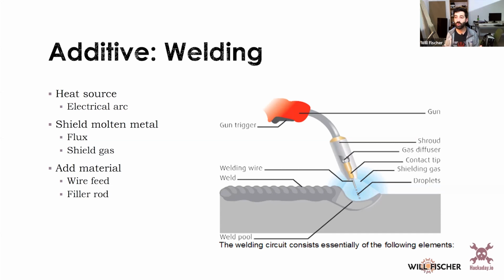And so I have two ways to do that. Either I can use flux, which is a material that floats to the surface of the weld pool, hardens, and then keeps the oxygen away from the weld while it's cooling. Or the much preferable way to do it is with shield gas. Shield gas displaces the oxygen around the weld and fills it in, typically with argon or CO2, or a blend of argon and CO2. Those are non-reactive or potentially even beneficial. The carbon in the CO2, if I remember, will react with the steel to increase the strength of the weld.